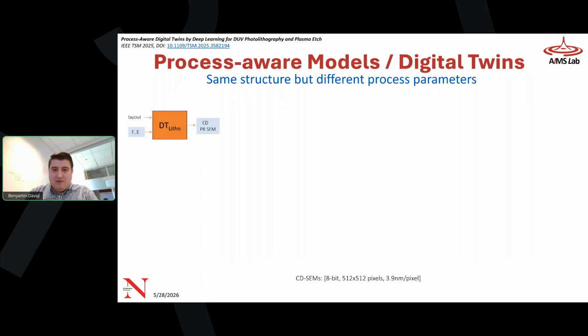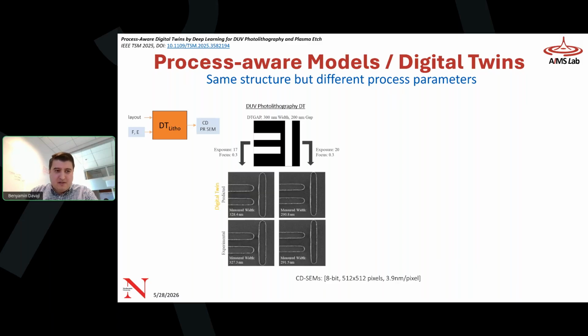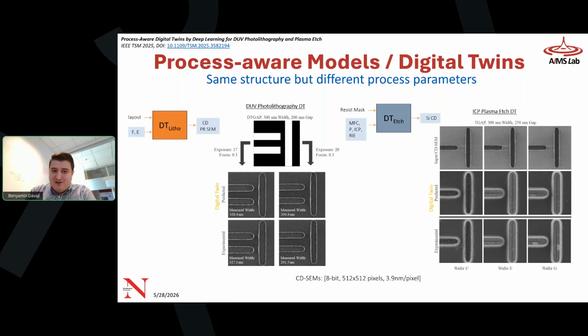Now, the last thing on semiconductor that I want to share is that you can not just learn translation, but you can add process parameters. For example, in the case of the positive resist, you can have process parameters to be tuned, and you can see for the same input, same layout, the outputs start differing when you expose the resist with different doses. And the digital twin exactly learns that. Bringing to everybody's attention, all of these images are 2 micron by 2 micron, and my pixel size is around 4 nanometer per pixel. So we are within the limitation of the measurement. And you can see the trends are very accurate. This can be done for more complex processes like etch, where you can compare the real and AI generated images, and you can see we learn very well.